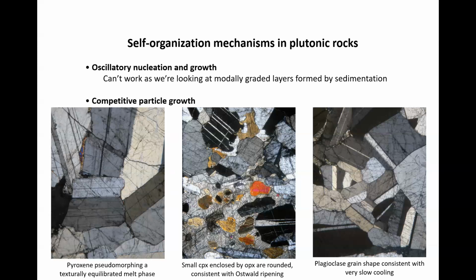And interestingly, what it also says is very high permeability, because if you've got a low dihedral angle, which you have for melt and plagioclase, then you've got total interconnectivity of a melt phase. So we've got very slow cooling, which is what we need. We've got very high permeability, which is also what we need for effective mass transport.